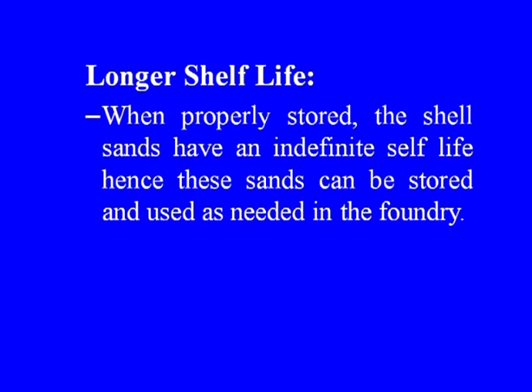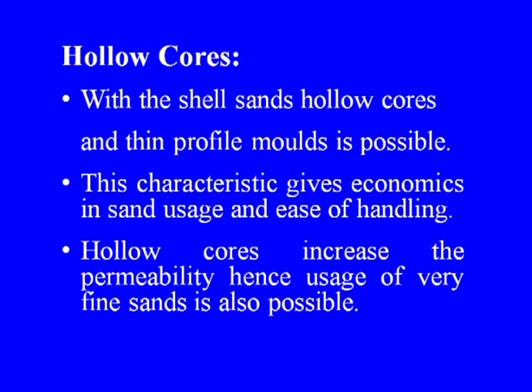The shell molding process accommodates deep draw patterns with less taper than conventional processes. Another advantage is longer shelf life — when properly stored, the shell sands have an indefinite shelf life and can be stored and used as needed in the foundry. With shell sands, hollow cores and thin profile molds are possible. This gives economics in sand usage, ease of handling, and increases permeability, making use of very fine sands possible.